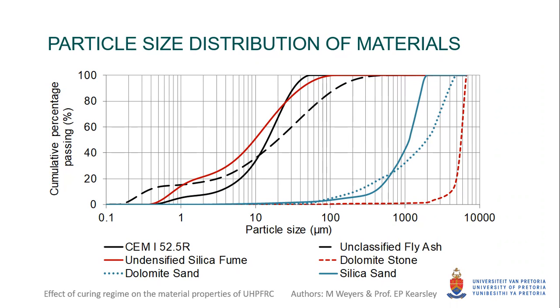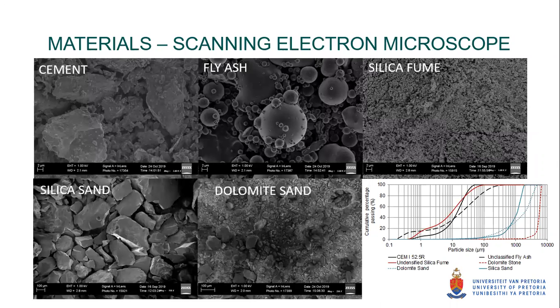A laser and ultrasound test was conducted on 2 samples from each material, and the average of the results was calculated and plotted as the particle size distribution. Scanning electron microscope images of cement, fly ash, and silica fume can be seen in the top 3 images. All 3 images have a scale of 2 micrometers, and this can be seen in the left bottom corner of each image. The images of silica sand and dolomite sand used are shown in the 2 bottom images, and the scale of both images is 100 micrometers.